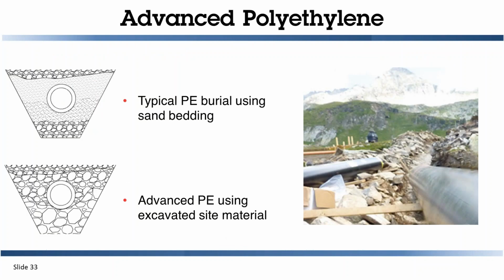That same strength characteristic that we see in that tensile test and allows us to apply it to oxidizing chemicals is actually good from the outside as well. So here's an application where a pipe was installed in a trench and the contractor was able to save significant cost by not having to truck sand in to lay the pipe on sand. Where it's allowed by code, this might be a useful method to install the advanced polyethylene pipe. You can use the excavated material to then bury the pipe, and you don't have to worry about point loads from the rocks.